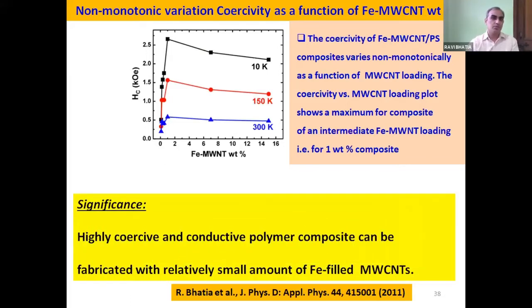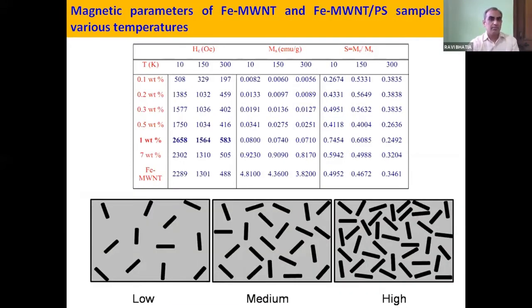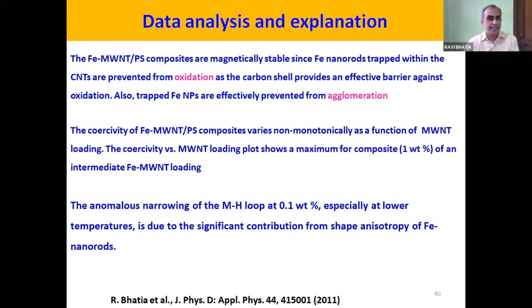Okay. So we could have a significance out of this work: highly coercive and conductive polymer composites can be fabricated with a very, very small amount of Fe-filled CNTs. The data analysis shows that this type of system in which the CNTs are encapsulated with magnetic nanoparticles forms a fantastic system because it prevents oxidation, and it prevents agglomeration.